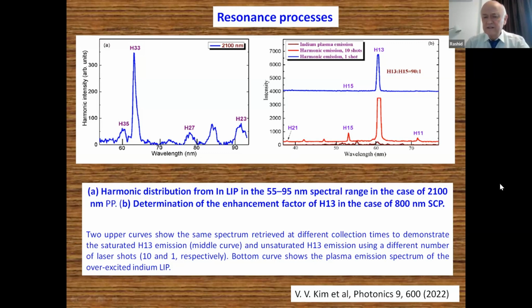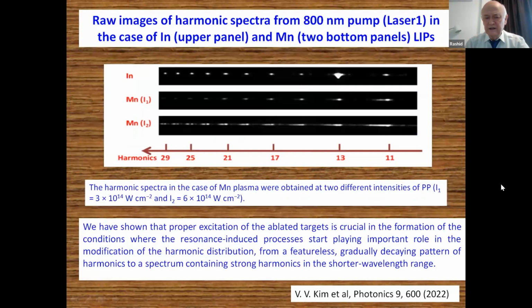So those studies have shown us that by analysis of the properties of plasma and combining them with features of some materials, we can observe very interesting processes. For example, here I just show a resonance harmonic from indium, and the same in manganese plasma, which shows blue-shifted high-order harmonics in that case.